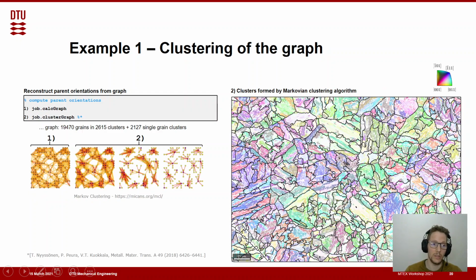In this way, the clustering algorithm slowly breaks the links to grains that are likely not belonging to an austenite grain, and it reinforces the links that are very likely related by an orientation relationship. This way, through many iterations, we get groups of nodes that are likely belonging to one austenite grain.